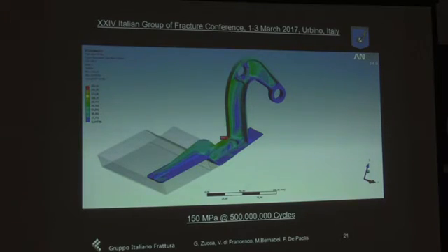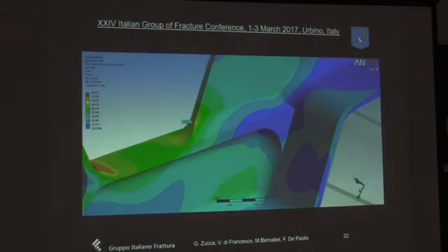Also, in the fracture initiation region the stress is under the fatigue limit, and we also have a very slight gradient of stress. So we know that fatigue is a question of stress gradient, and in this case we have no concurrence between the geometry, so the map of stress, and the fatigue initiation.